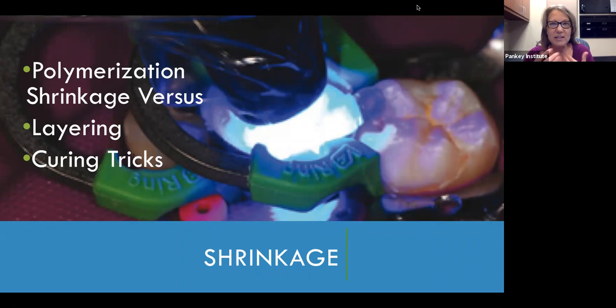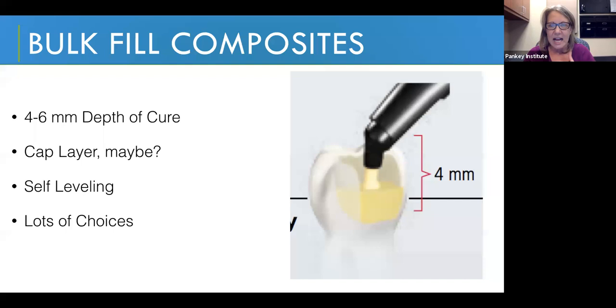We don't want to add any more stress to the marginal interface than we have to. Because of polymerization shrinkage, we were taught layering techniques — one millimeter layers and angled layers to reduce C factor. For years, we also used polymerization tricks: wave curing, ramp curing, using special curing with a lot of light to try to decrease total polymerization shrinkage. We had all of these factors and concerns about composite materials that had existed in dentistry for a very long time.